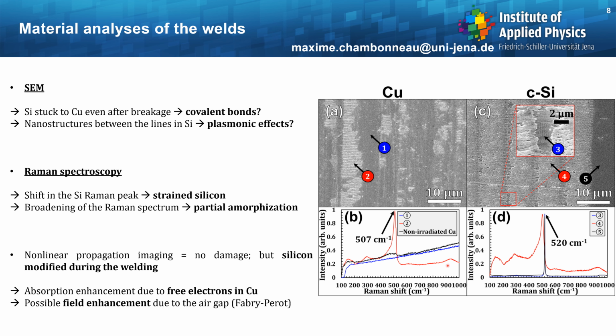It is worth noting that even if during nonlinear propagation imaging no damage is formed, silicon is modified during the welding. And this may originate from an absorption enhancement due to the free electrons in copper, and also a possible field enhancement due to the air gap through a Fabry-Perot effect.